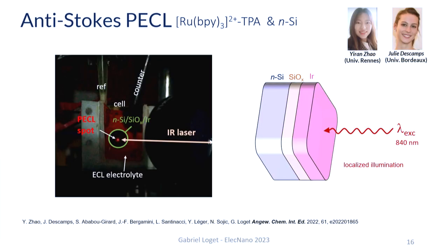So all these results were obtained with homogeneous illumination of the surface, and so all the immersed photoanode surface was emitting light. We can also do localized PECL, and there are two ways to do that. The first way is to use a very collimated near IR beam. If we are using a laser, we can generate a tiny spot of visible light.